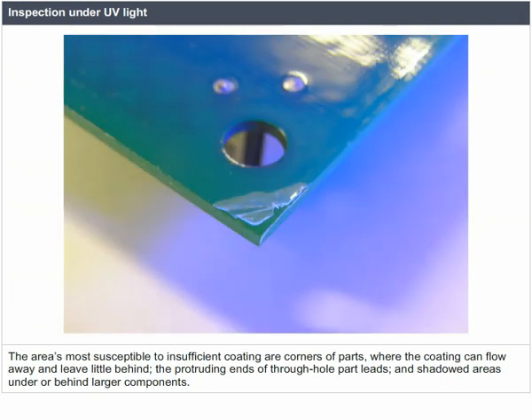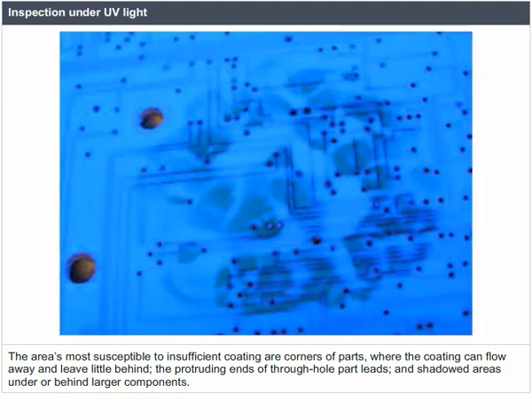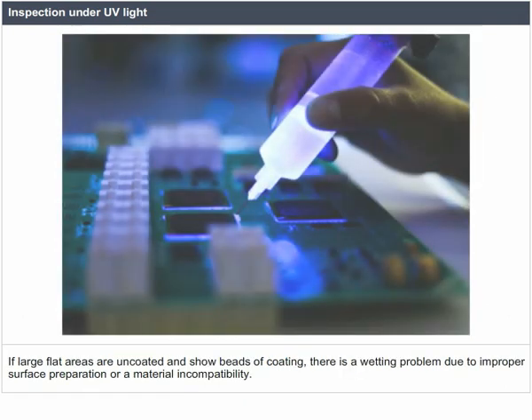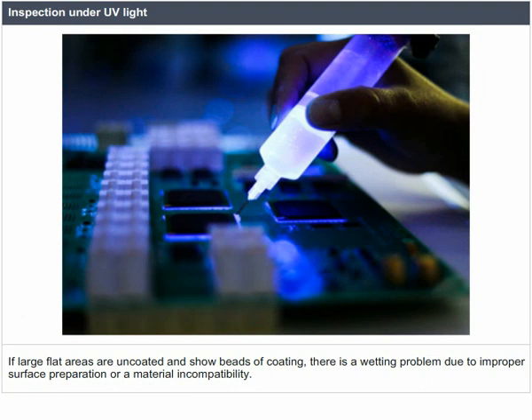The areas most susceptible to insufficient coating are corners of parts where the coating can flow away and leave little behind, the protruding ends of through-hole part leads, and the shadowed areas under or behind larger components. If large flat areas are uncoated and show beads of coating, there is a wetting problem due to improper surface preparation or a material incompatibility.